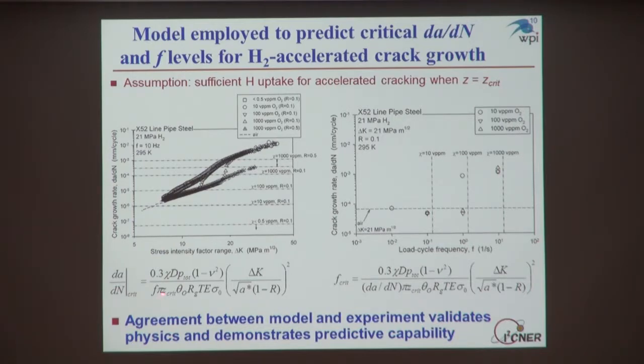So we're using the same critical level of oxygen over here to try to determine what is the critical frequency for activating these accelerated crack growth rates. And as I showed you before, for 10 part per million oxygen, this is the experimental data, the circles, we see the crack growth rate start to accelerate between a frequency of 0.1 and 1. And our model tells us that would happen at a frequency in that range. And so the predictive capability of the model seems to be quite good. And so this not only validates the physics that we've assumed in the model, but even this very simple model can give us some predictive capability that we could potentially even apply to engineering components.